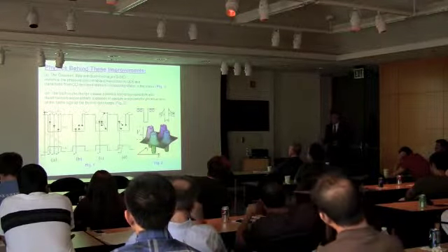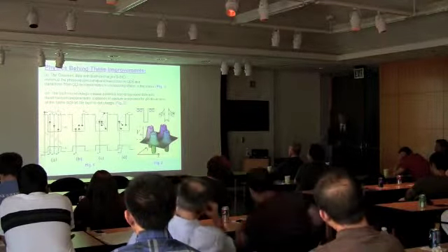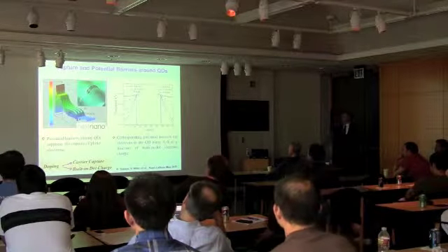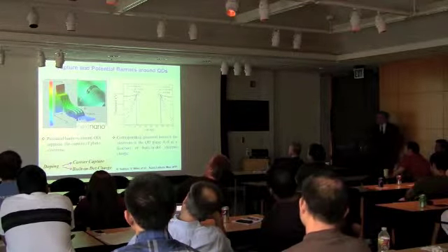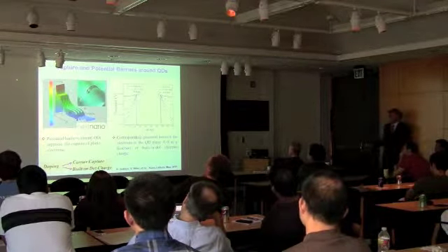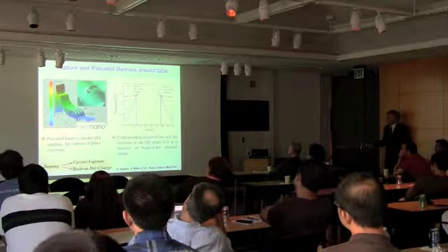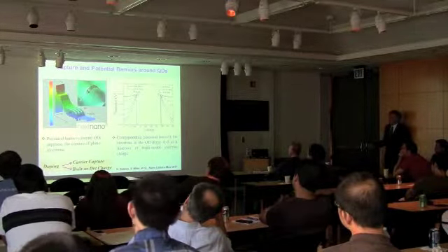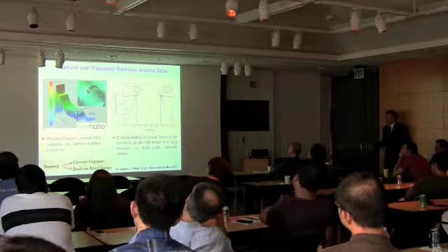electrons are now moving between the dots and they don't like to go in, and that is why we have reduced recombination. And here it shows that it's like a creek for the electrons, that they go between the dots. Depending on the number of dots, we show what is going on here. You see, this is a dot. In this simulation it is flat, but we have different sizes and different types of simulation, but the reason is